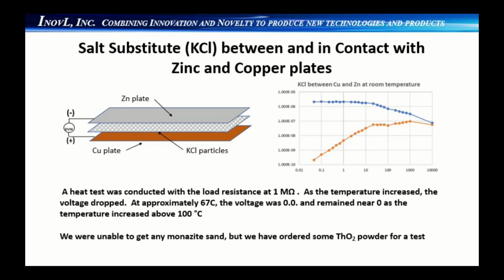This experiment is similar to the experiment Kramer conducted in 1924, where he used radioactive monazite sand to produce and measure a voltage and current. We didn't have any monazite sand, but we ordered some thorium dioxide powder that we plan to use after it arrives. In the meantime, we conducted a test using salt substitute, KCl, available at our local grocery store.